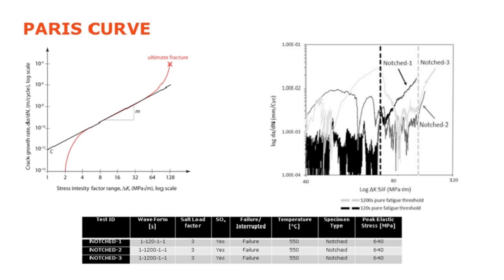I suppose it's also interesting to note that this is quite similar to the behaviour of single crystal superalloys between air and vacuum. We actually see that fatigue crack propagation in single crystal alloys is slightly less in air than it is in vacuum at high temperatures. So there are some comparisons that can be made there, and I suppose we see those effects more in single crystal alloys because we don't have grain boundary oxidation going on and other forms of crack propagation occurring.